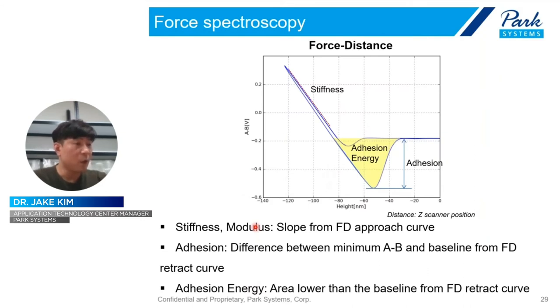So from this FD curve, we can obtain several mechanical properties. For example, stiffness or modulus from the slope of the FD approach curve, and the adhesion value, like adhesion force or energy, from the retract curve. Also, sample deformation, energy dissipation, or approach and retract stiffness can be calculated from just one FD curve.